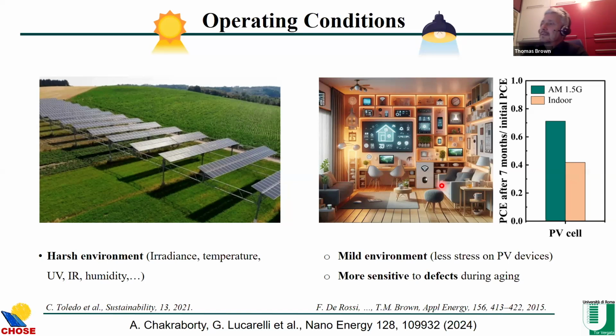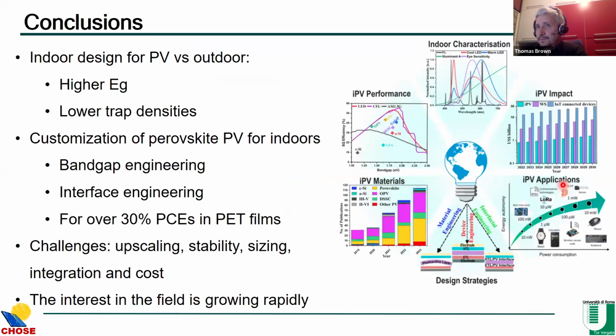On the other hand, and here we show a study we conducted on DSSCs, if there's any aging in the device, you'll see it more under low light conditions, because defects, of course, give rise to more problems, because recombination currents can become closer to the photo-generated currents, which are very low. So more needs to be done to understand these conditions.